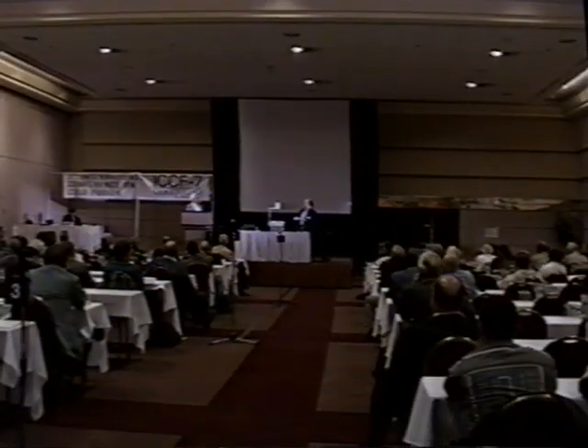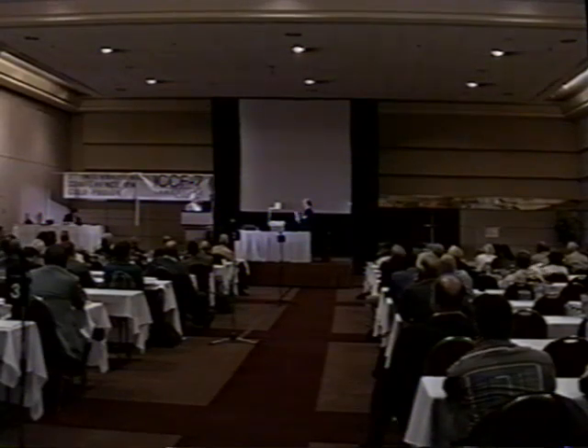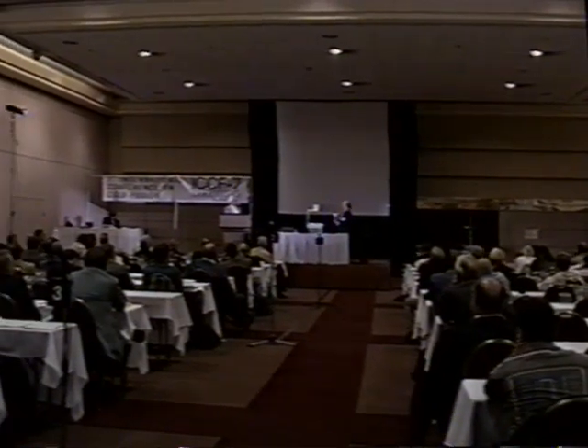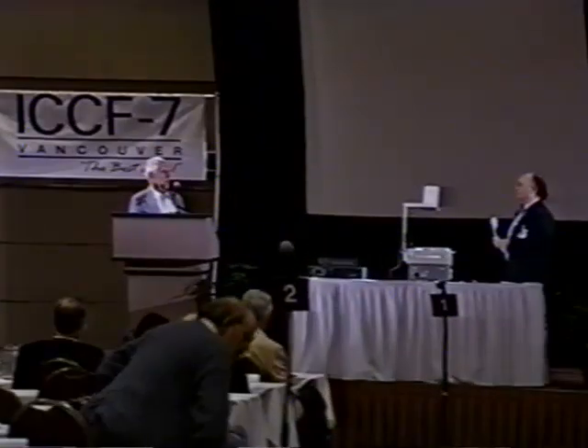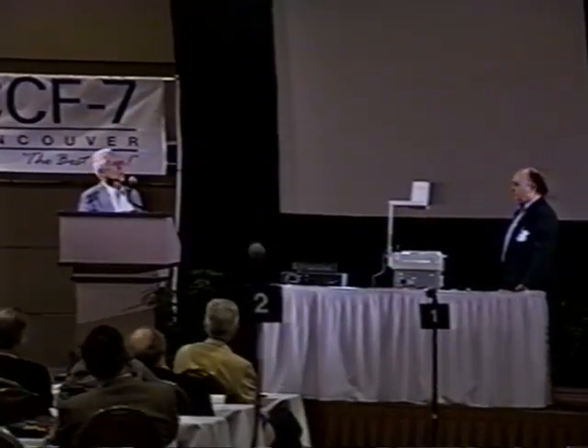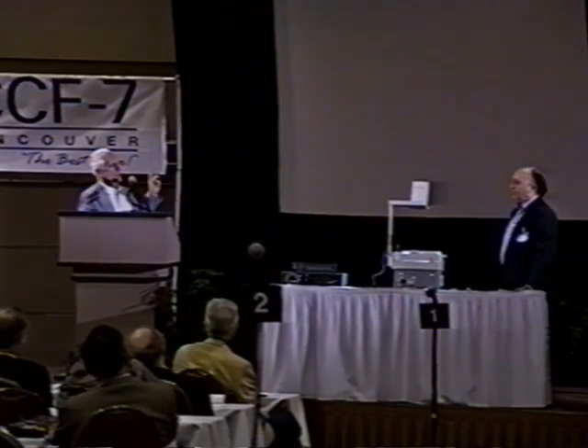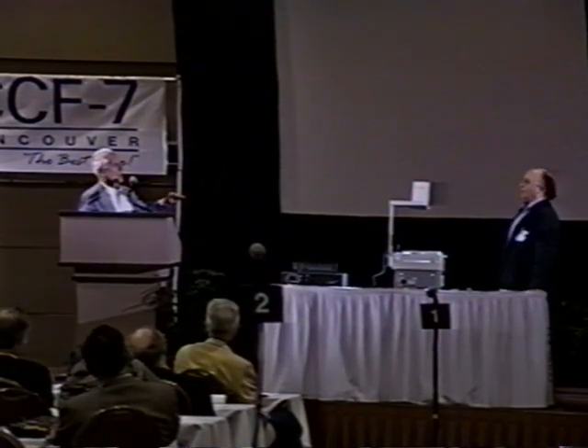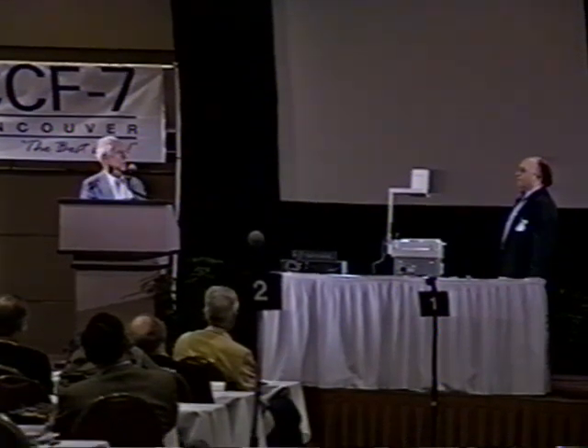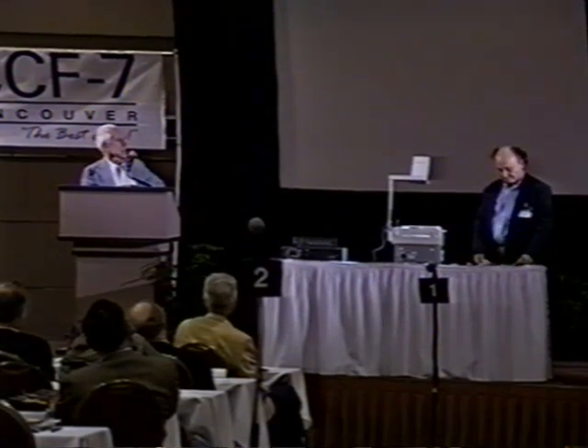A question. You measure temperature by following the resistance of the heater, right? Yes. In my experience, the temperature of the heater at constant wattage is a function of the environment of the deuterium or hydrogen atmosphere. Is it possible that in the situation where the temperature went down, you were really having better heat conductivity from the heater and therefore a lower temperature of the heater?